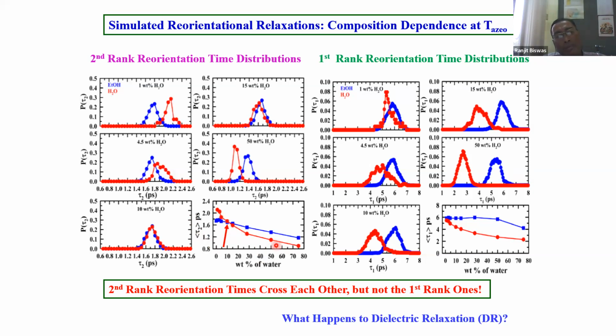And this decoupling has to do with the local structure. Something must be happening at the local hydrogen bond level, and their lifetimes, because these time scales are pretty small. And if you look at the hydrogen bond lifetime at that elevated temperature, it must be very comparable or even lower than this. So there is a competition between the rotation time and the hydrogen bond lifetime.